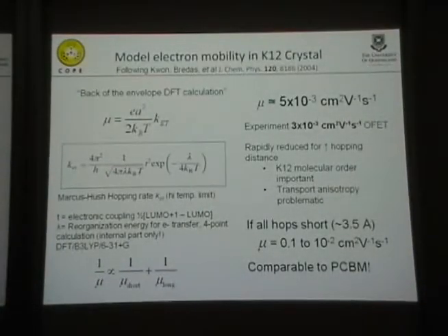Basically, any attempt to drive the electron in a different direction will result in a much lower mobility. So if we could magically remove the long hops and just make it all short hops, we end up with mobility comparable to PCBM, and we probably end up with a 5 or 6% cell.